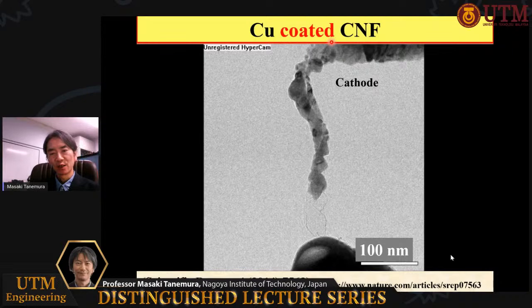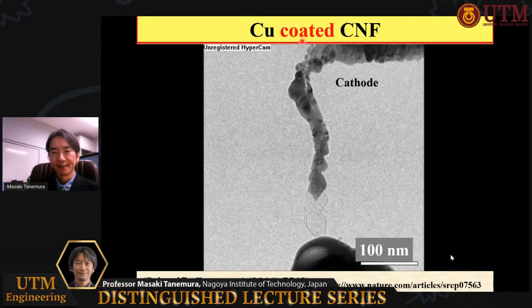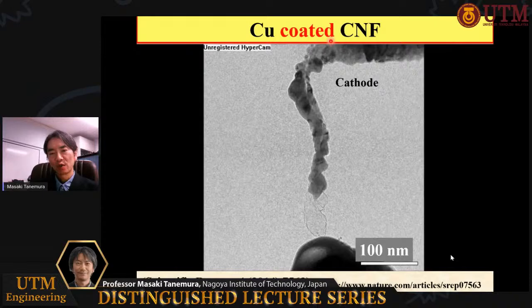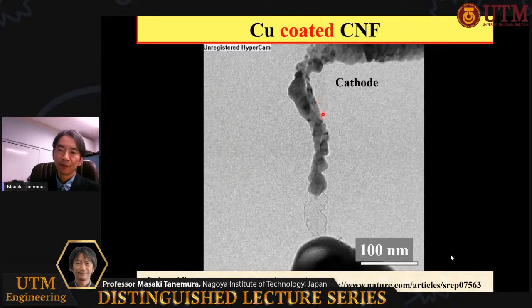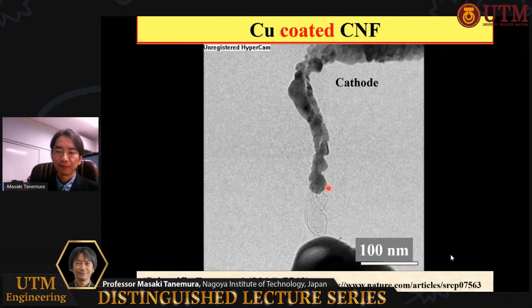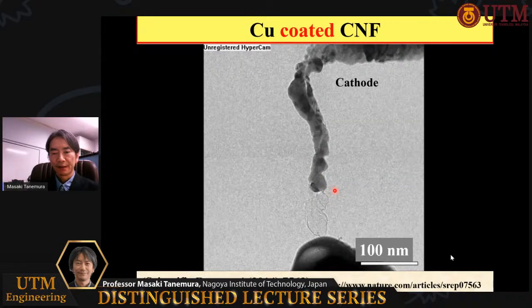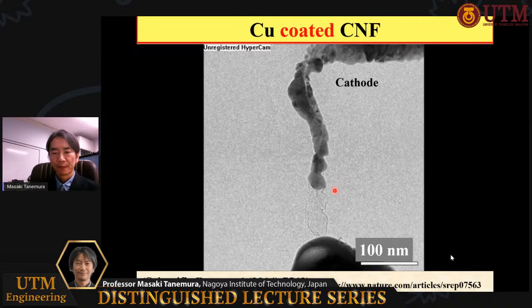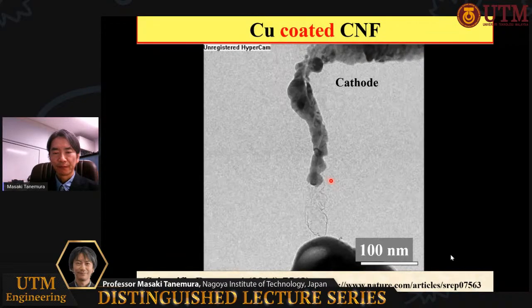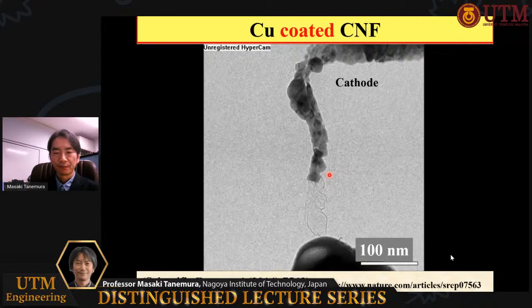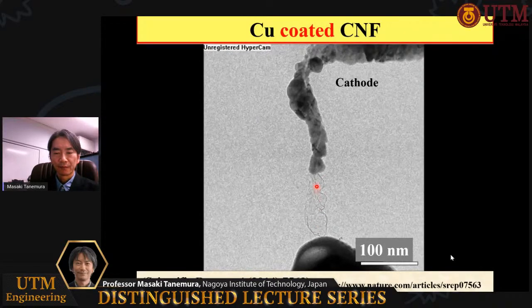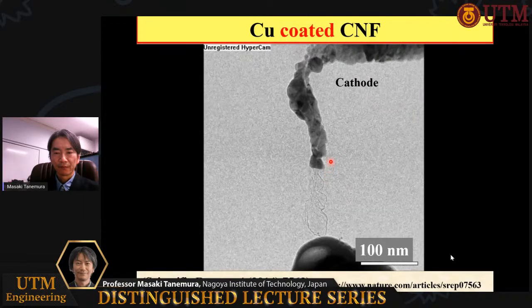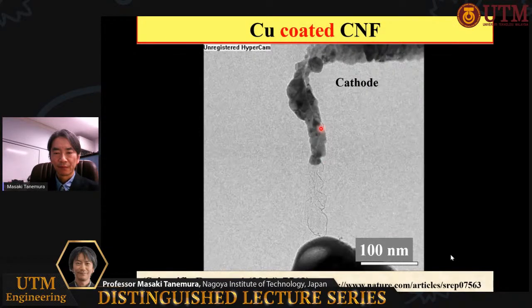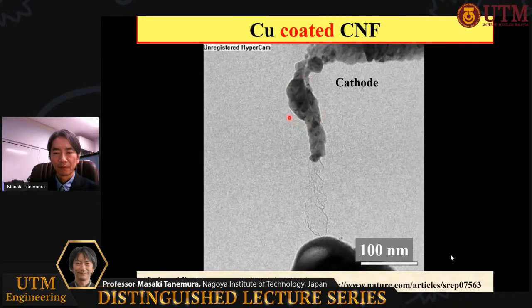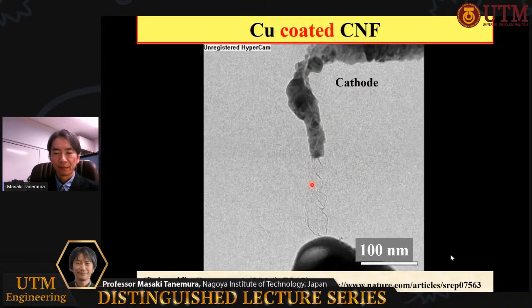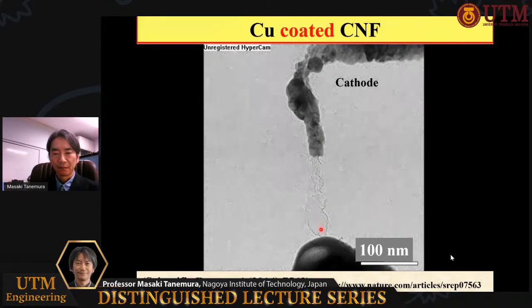This is the copper-coated carbon nanofiber case. Carbon nanofiber was covered with thin copper film and we applied the voltage. You see, with increasing the voltage, the movement of copper thin film occurs. Here, you see the increase in the transparent area and shrinking thin film. Here becomes thicker. This relatively transparent wire is graphene nanowire, and flake size is larger than the previous one.